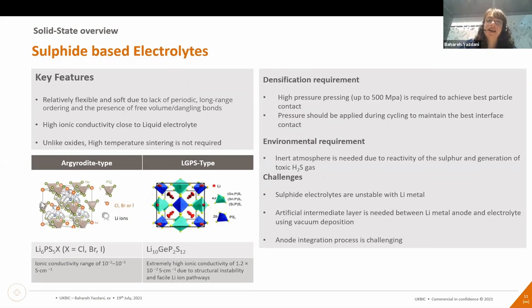For sulfide-based, they have very good advantages: they are very flexible, and they have very high ionic conductivity. And they don't need as high temperature sintering, because their crystallographic structure is not as ordered as oxide-based, they don't have the long range ordering, and their crystallographic structure has very open areas for lithium ions for movement and hopping. So that's a very good point regarding the manufacturing costs. However, there are challenges as well, which is they need high pressure and pressing to contact the grains together.